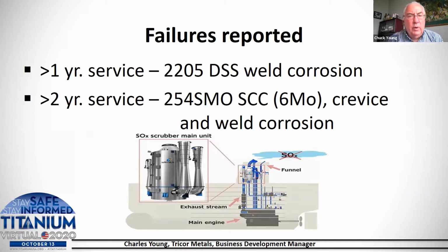2205 duplex stainless steel weld corrosion after just a little over 1 year, and a little over 2 years service, some 254 SMO, that's the 6 moly, crevice and weld corrosion. Now, the key here is 2205 has to be welded correctly. Otherwise, you get a change in the ferrite to austenite ratio in the weld or in the heat affected zone, and that could cause it to suffer corrosion fairly fast. So that's probably what happened here, the welding wasn't done correctly. 254 SMO crevice corrosion would be expected if you had under deposits in the scrubber, as well as weld corrosion because of welding problems. And again, that just shows this is a Wartsila scrubber out of Poland there, where their scrubber goes and what it looks like.